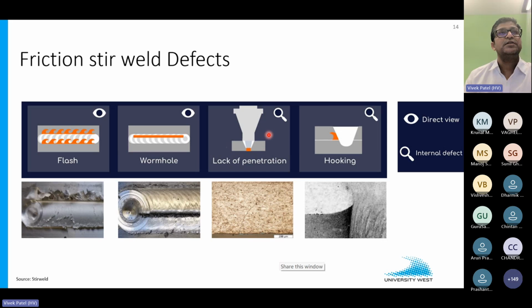Then other defects that we can't see from the surface, where we need a microscope to see the cross section. It's a lack of penetration. You can see it here. That's quite common in the case of butt welds. And in the case of lap joints, you have some hooking. Hooking is like a conventional microstructural feature that is present in friction stir welding when you have a lap joint. And with this hooking, the higher the hook, you lose some strength in the joint when you test from a static strength or fatigue perspective. So the main focus is to try to have the minimum height of the hook so you can have a stronger joint at the end. So these two defects are only visible through a microscope. So you need to have a cross section.